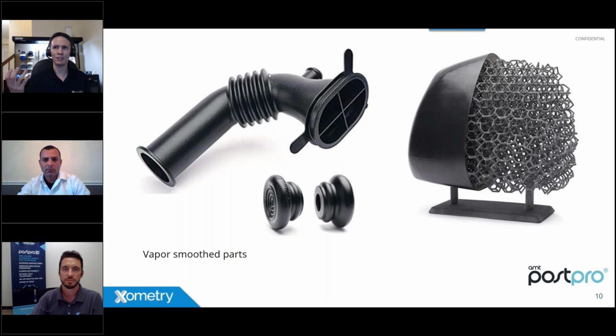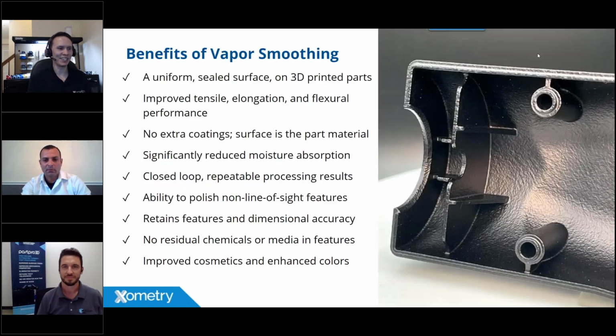Because you're condensing the solvent, the finishing agent, it's condensing all over the part, so it covers all surfaces and does the work. And it's pretty amazing. We were doing some tests with some closed-off tubes, and after we finished smoothing, I actually took a flash on the inside, and you see a reflection, and you're like, oh my gosh, this actually polished the inside of that feature as well, which is something that traditionally is extremely difficult to do. Exactly.